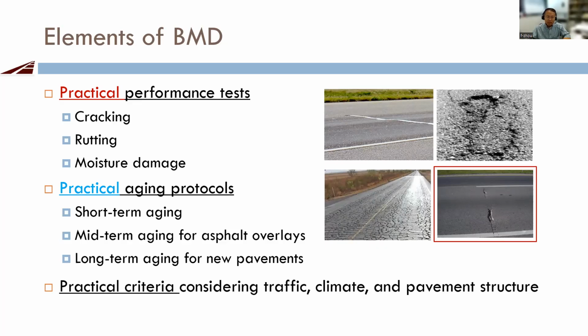Another aspect is the aging protocol, because we all know asphalt mixes age. Their mix performance changes with aging. The more you age the mix, the better the rutting resistance and the poorer the cracking resistance. So we have to talk about what kind of short-term aging protocol we should use. Do we need to consider mid-term aging for asphalt overlays? Mid-term aging is a terminology we coined several years ago, specifically for asphalt overlays, because with an asphalt overlay, normally we see 4 years, maybe 3 years, depending on how thick your overlay is, and you see lots of cracking. That's probably when you have already finished your aging in terms of performance. That's why we came up with mid-term aging.